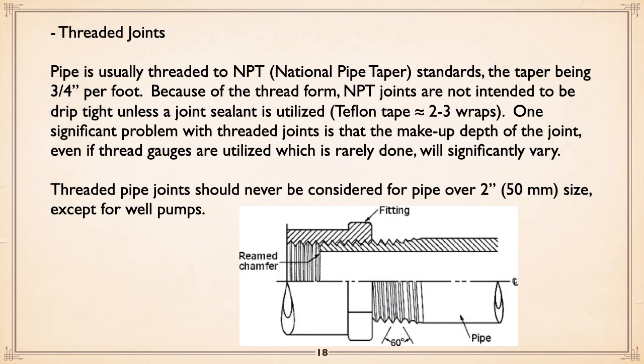Now, connecting. Threaded joints. Pipe is usually threaded to NPT, National Pipe Taper Standards, the taper being 3/4 of an inch per foot. Because of the thread form, NPT joints are not intended to be drip tight unless a joint sealant is used. If you use Teflon tape, which is quite common, 2 to 3 wraps. I've seen, and there was a problem at one time, people will put several wraps on, think, oh, we get better sealing. What happens is the Teflon, because it's in so loose, will actually move a little bit under pressure, and a few months later, you got a leaky joint. So 2 to 3 wraps is preferred.